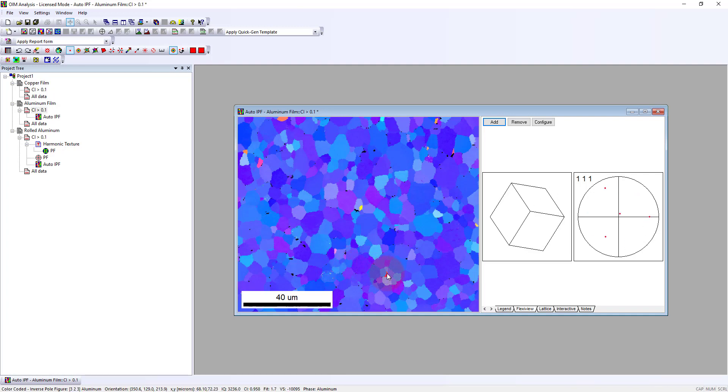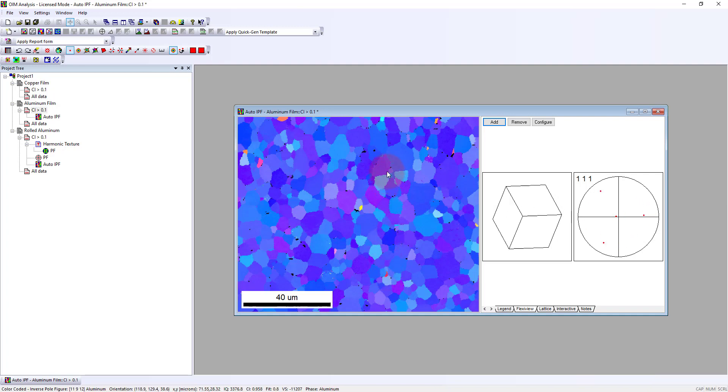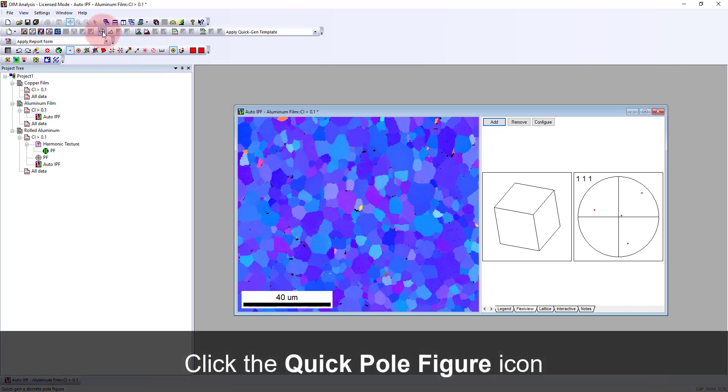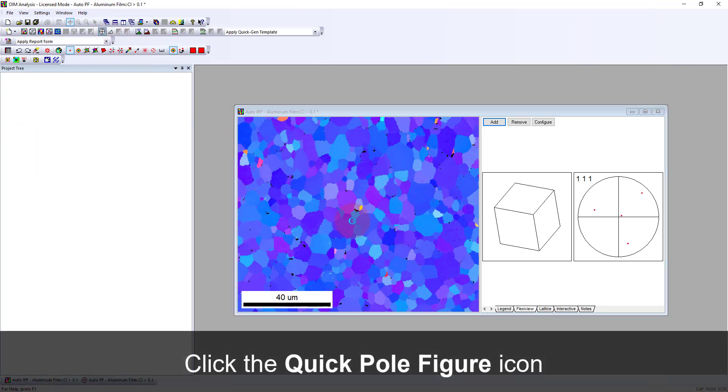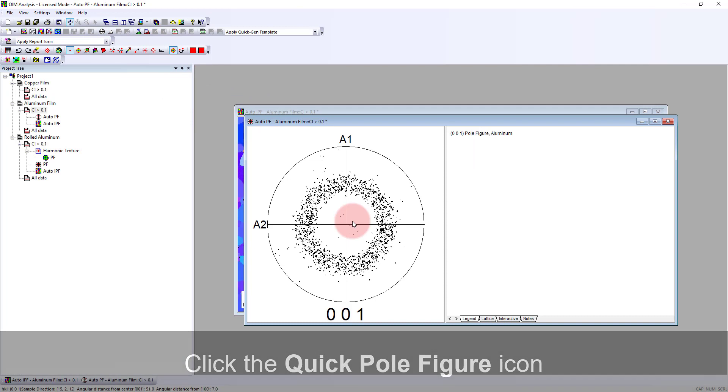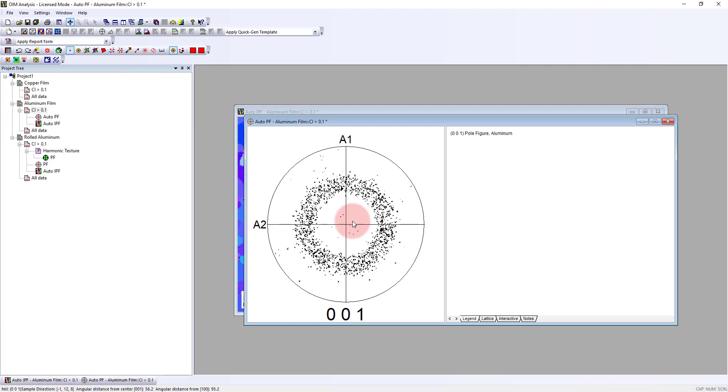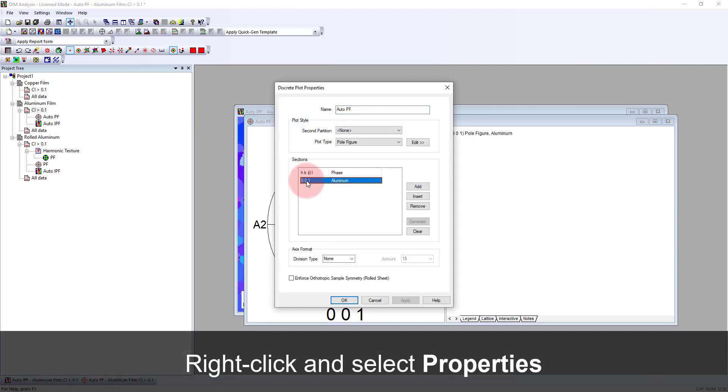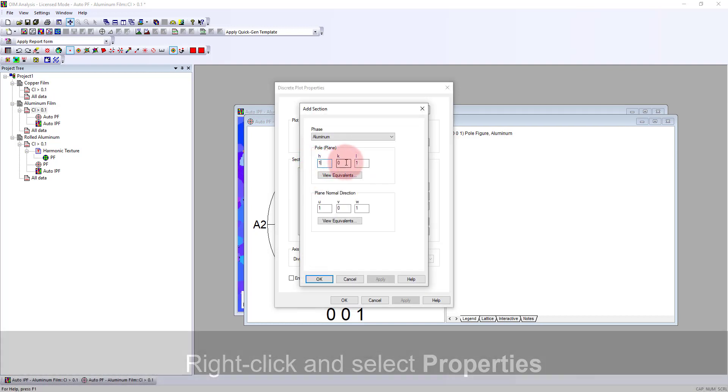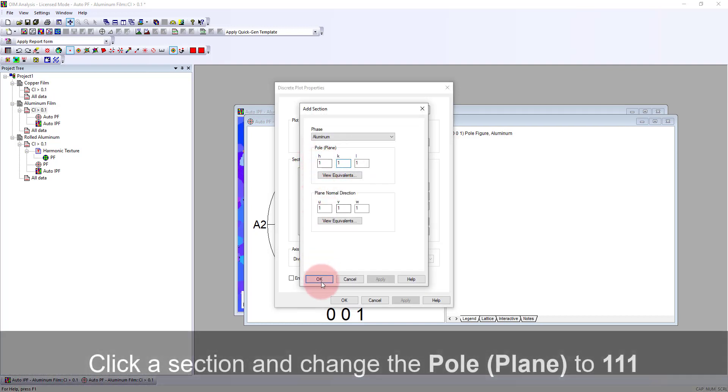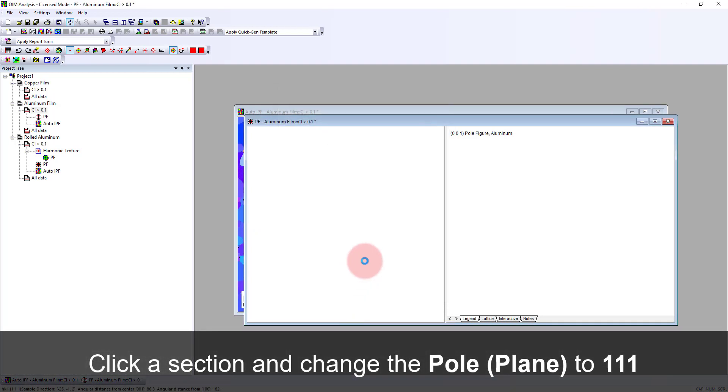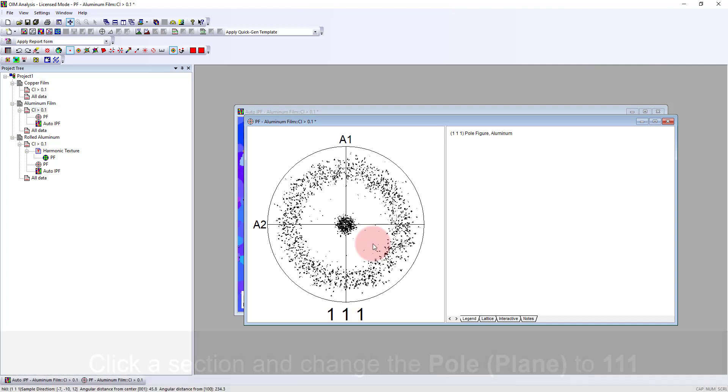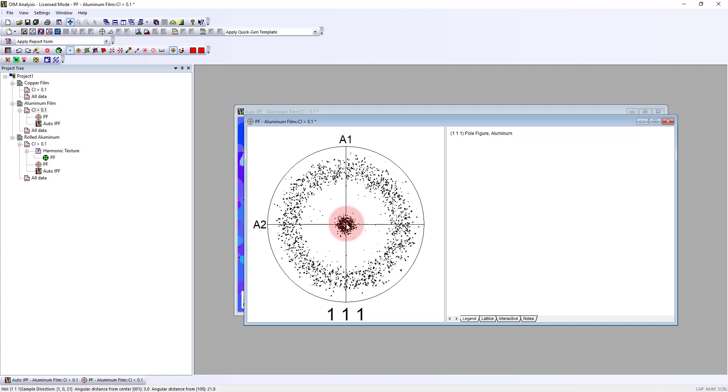That's why those are all blue. But when we look at the outer spokes, which are the other 111 poles for that orientation, there are four coming out at us, sort of radially distributed around the center. I'll create a quick pole figure here, and we see that creates sort of an annular distribution. I'll change this to the 111 pole figure, and we can see what's described as a fiber texture. The surface normal is aligned in the center of this pole figure, nearly all in the center, but there's this distribution radially around where there's freedom that it can be distributed randomly around that.